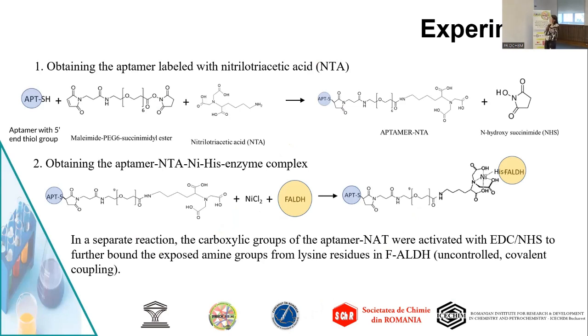Here you can see the scheme of my experiments. We started from the aptamer with the thiol end group that was attached to nitrilotriacetic acid through maleimide, and we obtained that complex that you can see there. After that, as I said previously, FALDH has an affinity for nitrilotriacetic acid. So we attach that complex to FALDH in the presence of nickel chloride, and we obtained our product of interest. These were our main reactions.